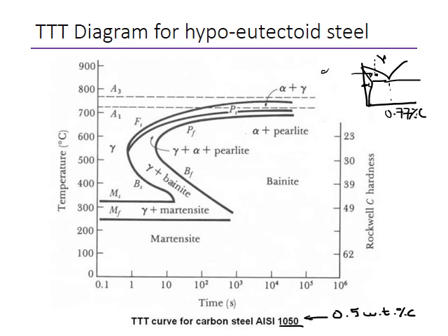So these steels will change from 100% austenite into this region, and here we have alpha. So in this region we have a mixture of alpha plus austenite. Remember that this is called primary alpha. And when we are below this, we have either alpha plus cementite, and remember that this is option A of our problem solving on the microstructure, or we might prefer to refer to the pearlite.